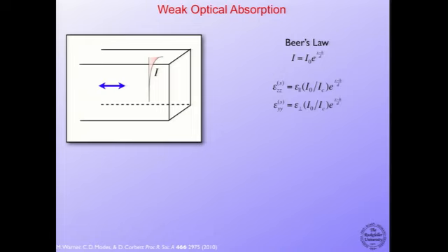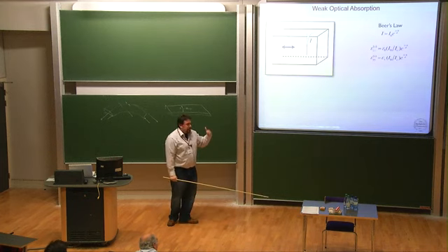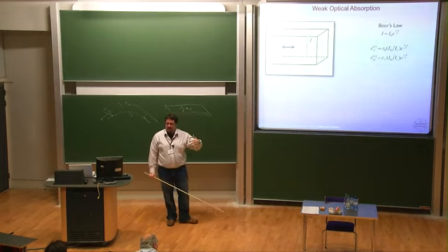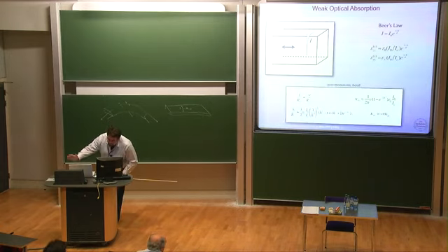There's a high intensity, and then that intensity falls off by Beer's law into the sample, so it's just an exponential, and you can write down this gradient in the strain. You're getting differences in the length changes because deeper into the material, it sees less of the light that's activating it. Again, turning the crank.